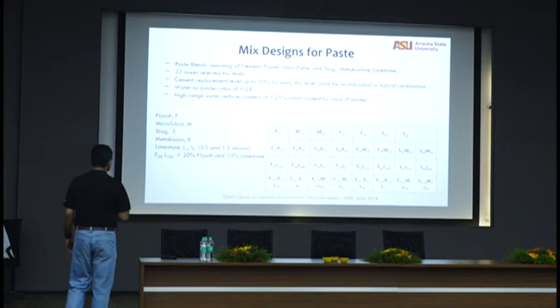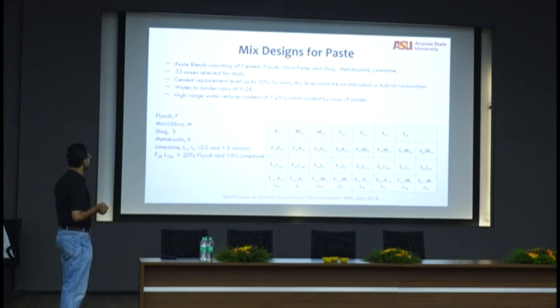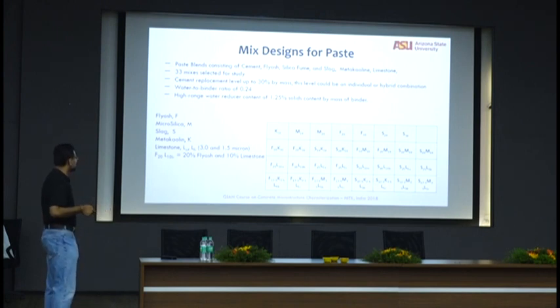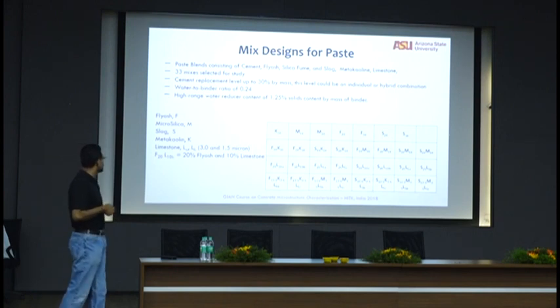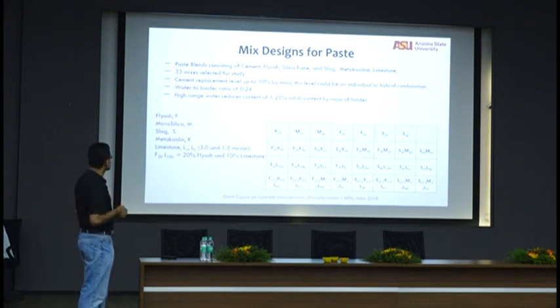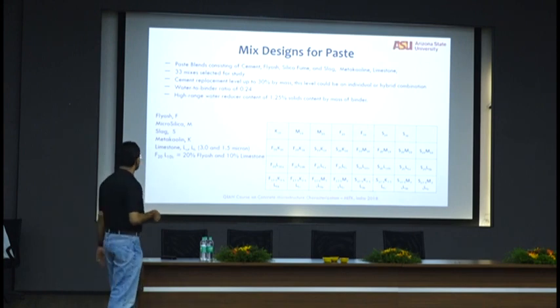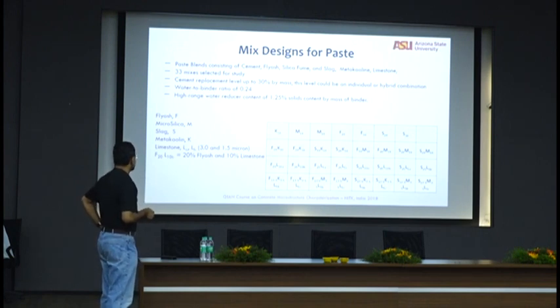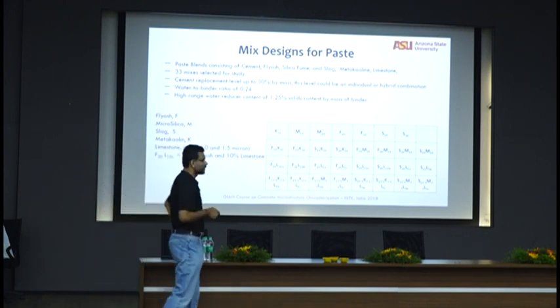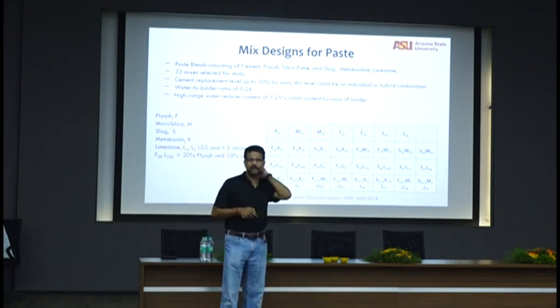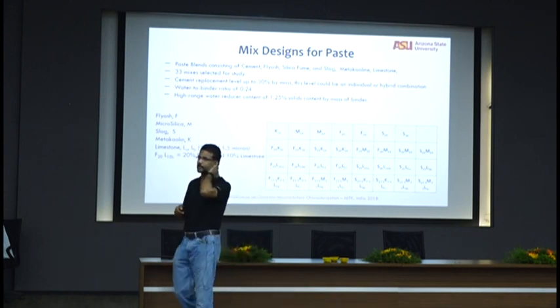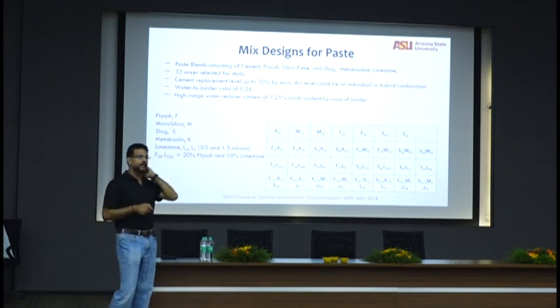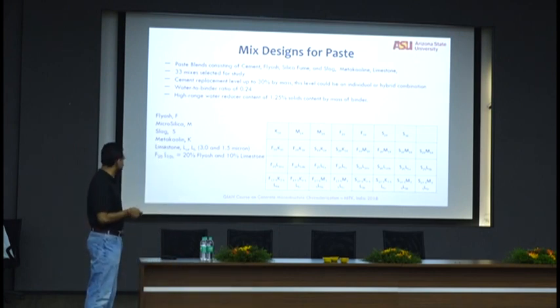So we initially started with cement, fly ash, silica fume, slag, metakaolin and limestone, created a large matrix of mix, about 33 mixes, cement replacement level up to 30% by mass. We've even gone up to 50% effectively. We started with a water binder ratio of 0.24 and then went down to 0.18, and high range water reducer of 1.25% solids by mass. That translates to about 5% of superplasticizer by weight of cement. Very high amounts of admixtures.